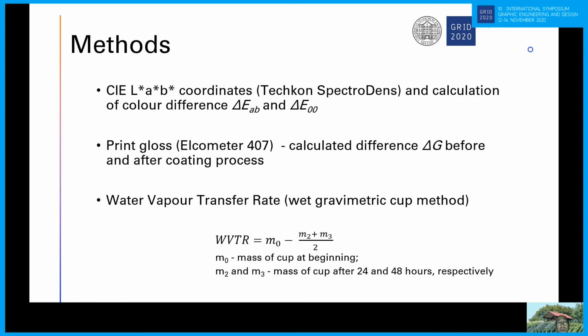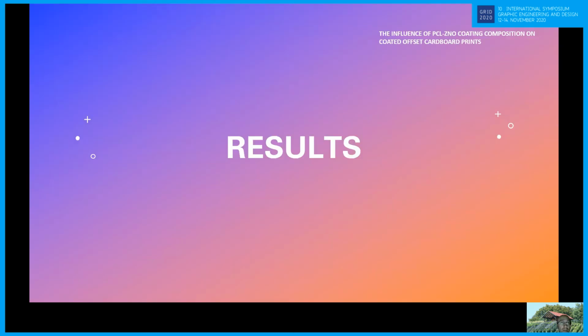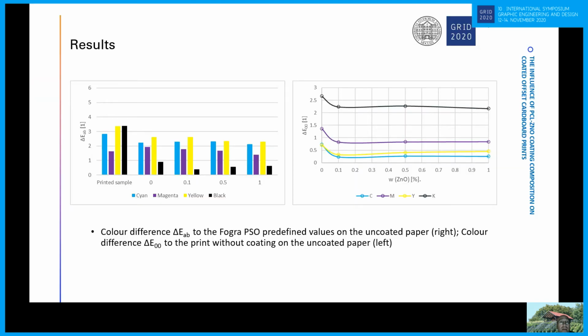Similar to that, we measured print gloss with Elcometer 407, and we calculated the difference delta G. We name it delta G by calculating the difference between the print before and after the coating process. And in the end, we measured water vapor transfer rate by using the equation seen in the slide. We used the wet gravimetric cup method. And we come to the results part, and the results say, so here you can see on the left is